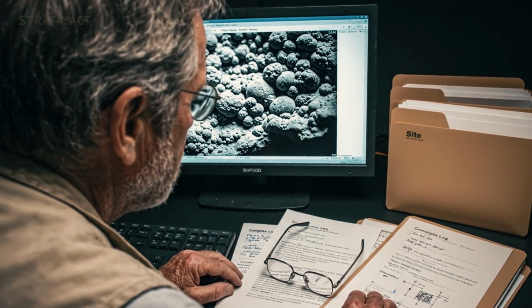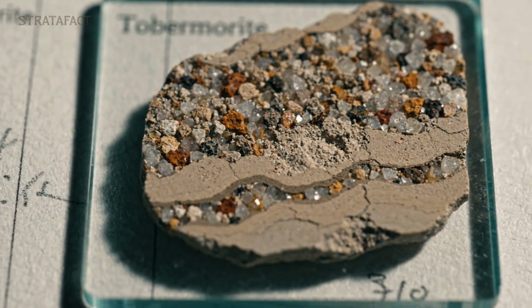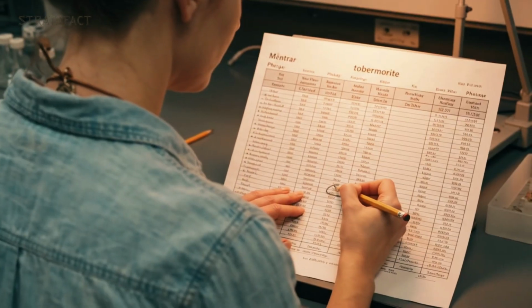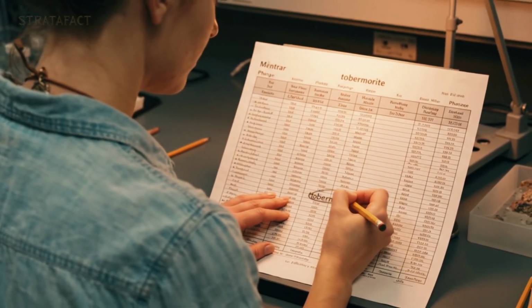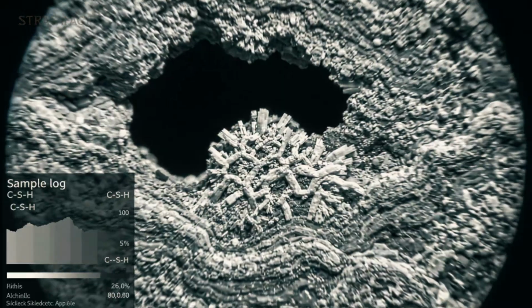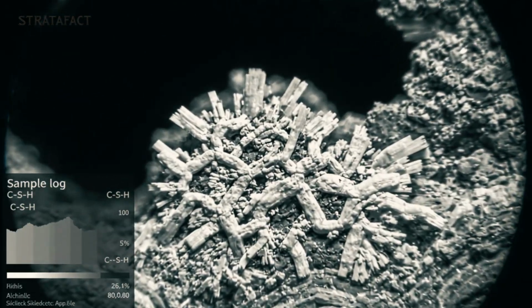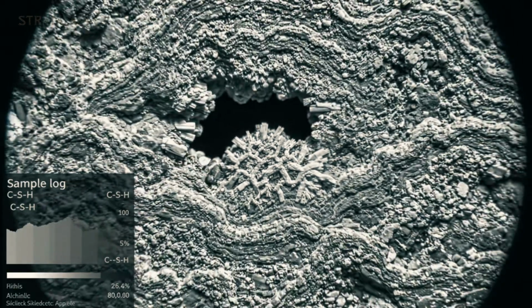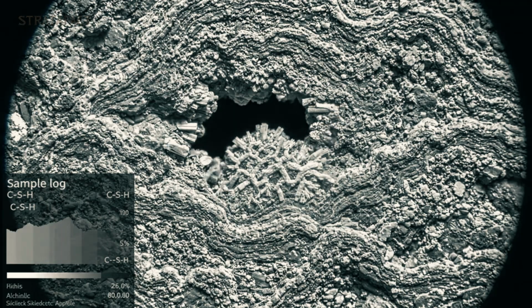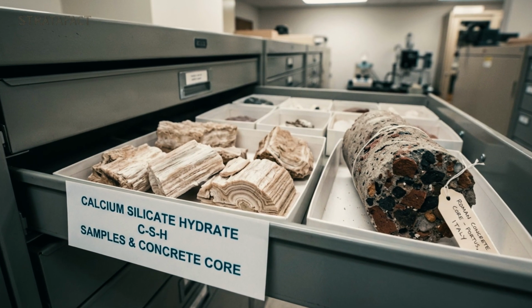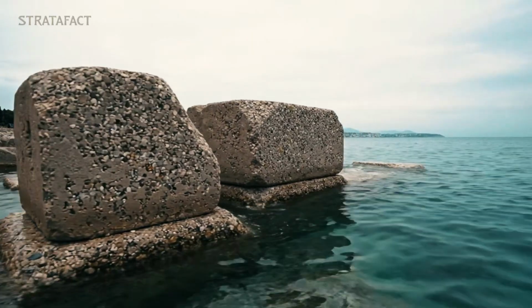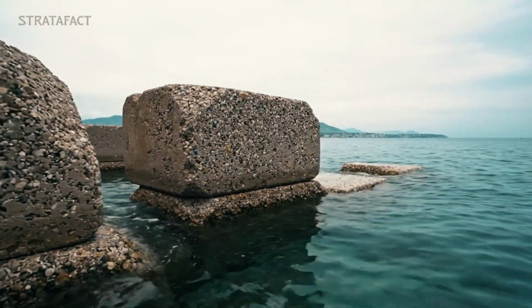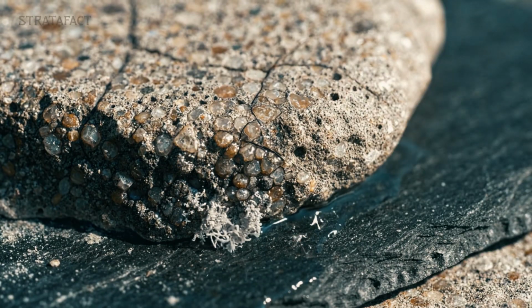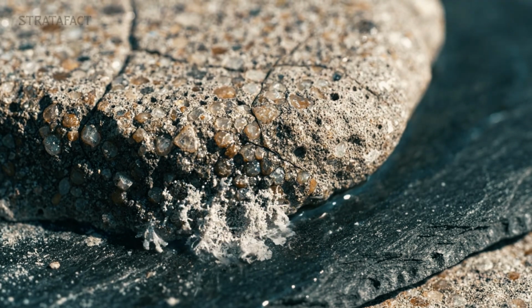What the analysis found across all three, despite these differences, was the same unexpected mineral, tobermorite, a calcium silicate hydrate with a specific layered crystal structure that forms slowly at lower temperatures than the conditions under which it was previously thought to crystallize. The conventional understanding of tobermorite formation required elevated temperatures, hydrothermal conditions well above ambient, that would not be present in a marine concrete structure sitting in Mediterranean seawater.